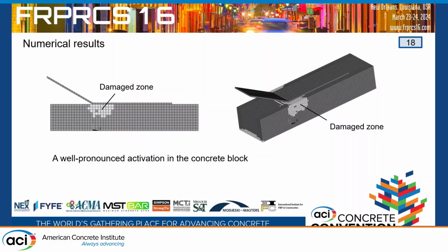Yeah, hey there. Did you observe in your numerical simulations stable crack growth followed by dynamic crack growth? Because in my experiments, I observed that the IC debonding happens first slowly, until you gain enough critical debonding length, and then it goes, so it is more dynamic, and it is drawback.